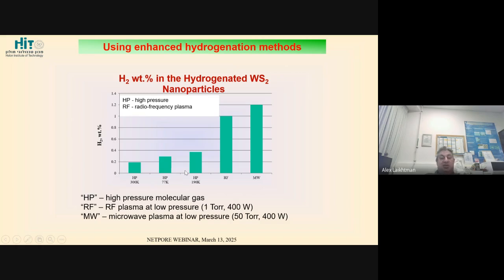Then we decided that molecular hydrogen as is not good, and so we have to do some kind of excitation. And the excitation was either RF plasma. From this research, we later came to other applications when we're using RF plasma, and also microwave plasma. So here you can see the weight percent. With microwave plasma, we obtained about 1.2, even in some cases 1.28%.